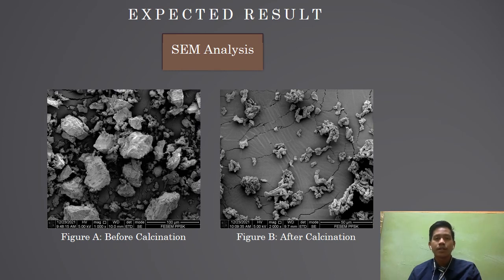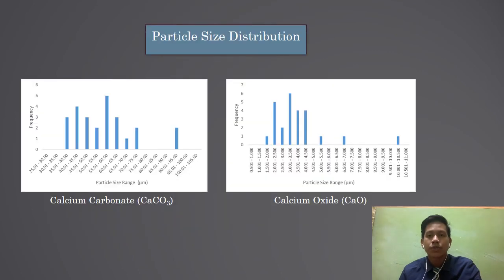This preliminary study was conducted using eggshell alone, where the eggshell was calcined at 900 degrees Celsius for 2 hours. The same analysis of the eggshell: Figure A represents the eggshell before the calcination process, while Figure B represents the eggshell after the calcination process. The graphs show the particle size distribution of eggshell.